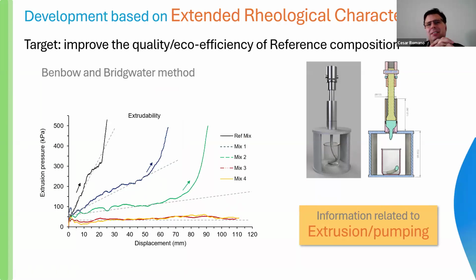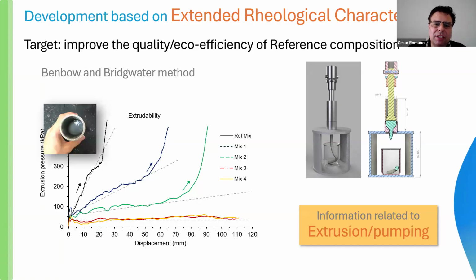Here it's possible to differentiate the materials. You remember that we didn't have differences between the mixes 3 and 4 with the reference mix during the stage of mixing and pumping. But we have considerable differences here when we apply a method that is specifically to evaluate the extrudability of the material. And it was possible also to see that when we evaluated the reference mix, we had phase segregation here, phase separation here. So these compositions presented very good extrudability capacity.